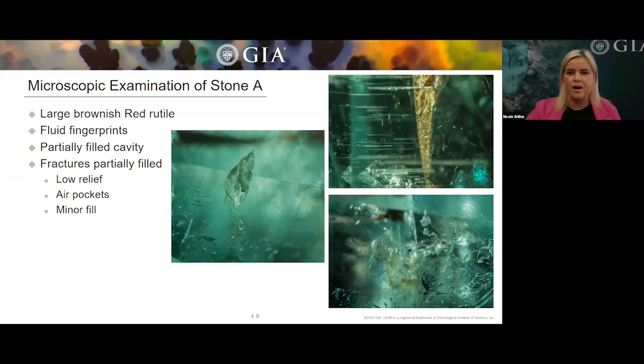One has evidence of flattened gas bubbles, and you can see in this bottom photo that there is a blue flash effect going on. The gemologist also noted that there is a cavity that breaks the surface, as you can see in this middle photo. It's actually a filled cavity. So the gemologist will note on the report that not only is there fracture filling present, but also a filled cavity. The gemologist must also decide whether the filling is minor, moderate, or significant. They note that the fractures are smaller, so this will go out as an F1, minor filling.